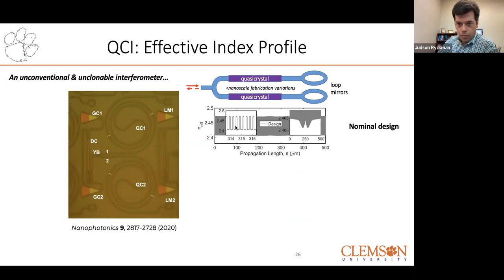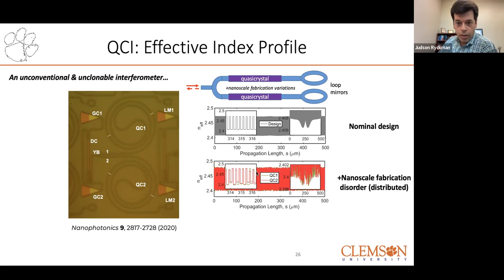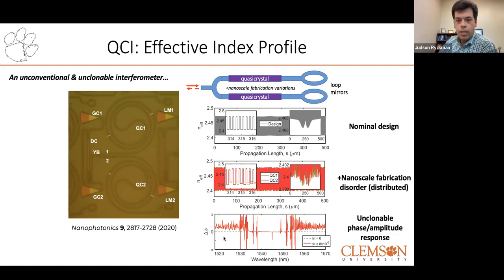So how do we do this? Well, without getting too detailed here, we have this effective index profile, which you can think of sort of like the electron particle in a box, kind of standard quantum mechanics, but instead here think of optics. We have some potential landscape of high and low refractive index that could potentially confine or transport Bloch modes through it. But in the fabrication, there's a disorder that occurs. And this disorder is not repeatable device to device, and it introduces lots of interesting effects. Some states become localized, others just shift their optical response. And so the output of this particular interferometer becomes very disordered. There's actually signatures of Anderson localization with some of these resonances, but the phase spectrum and the amplitude spectrum become unclonable from device to device.